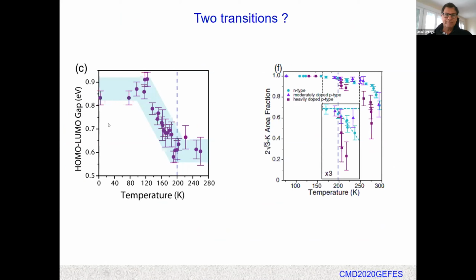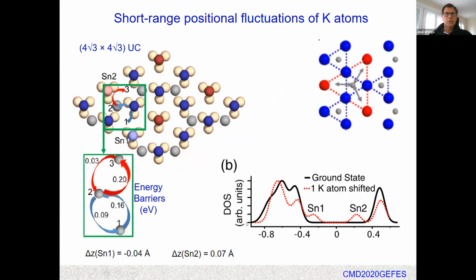So this is the √3 by √3 phase. Still, we need to understand what is going on before 200 Kelvin, where we have this decrease of the HOMO-LUMO gap. And as I said before, this is taking place where we still have a 100% surface in the ground state. In order to understand that, we have analyzed the short-range positional fluctuations of the potassium atoms. For this purpose, we use a 4√3 by 4√3 unit cell, which is a big one.